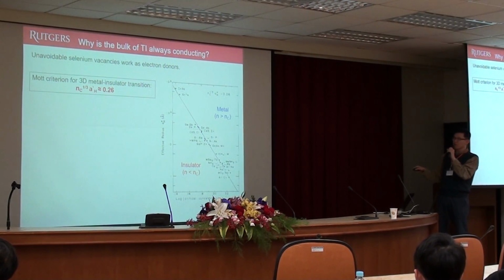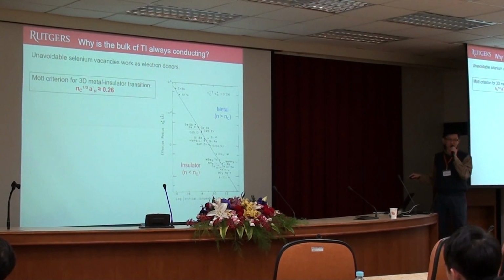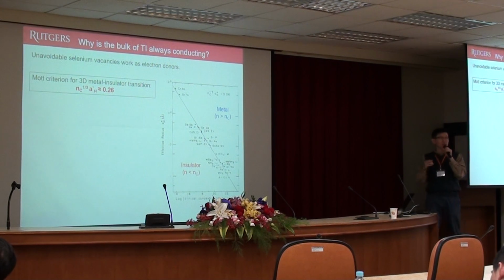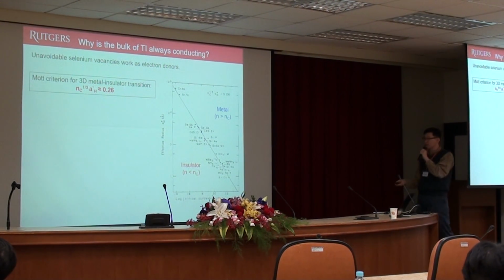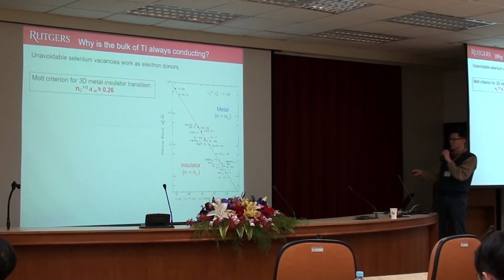So take silicon as an example. Silicon is the most widely known. If your doping density is below, let's say, 10 to the 18 per cubic centimeter, then the carriers freeze as you cool down. They are conducting at room temperature, but if you cool it down, they all freeze. So at low temperature, they are completely insulating, if your doping density is lower than this critical density.